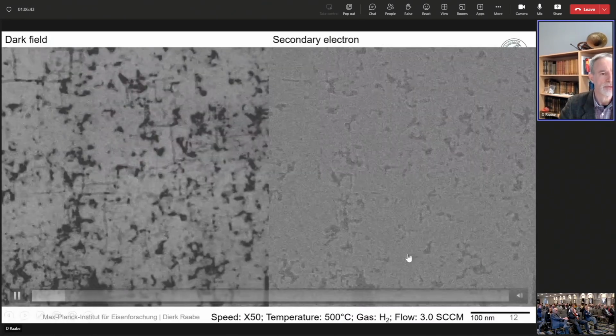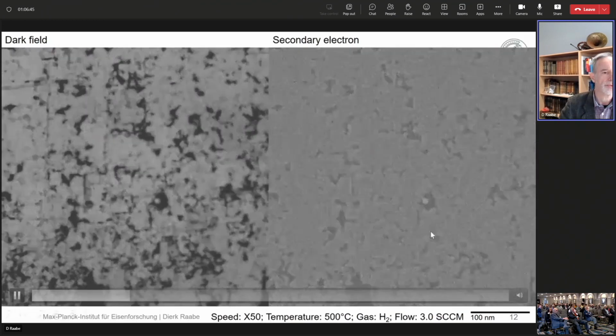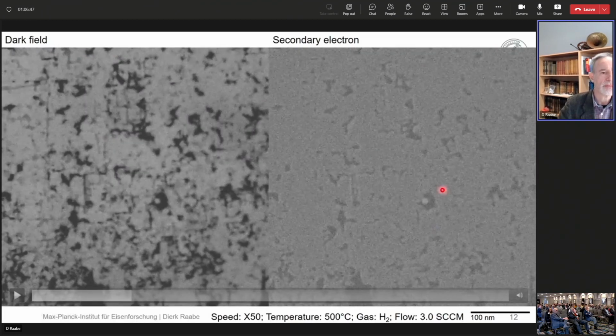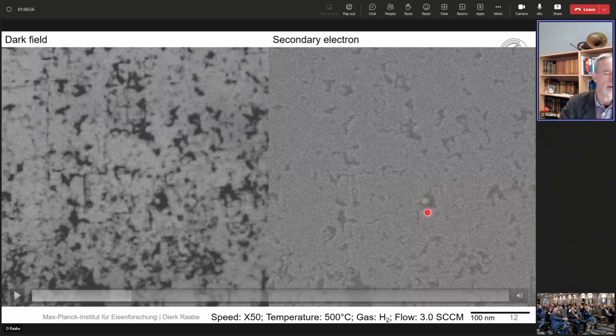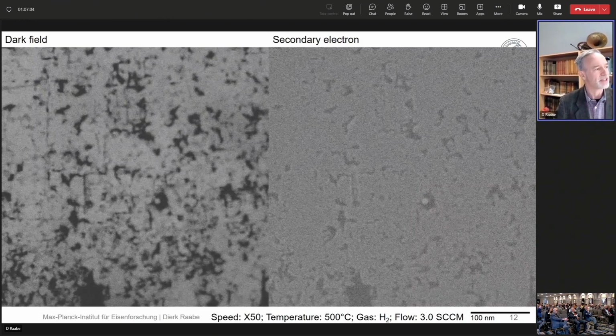And please be aware, note here where maybe you see the pointer. I stopped the movie here, and I hope you can see it. You see maybe this bright appearing little sphere, this little bullet type of feature here in this otherwise free volume area. And the free volume is a part of that transformation. It's thermodynamically very, very interesting because you cannot undergo these transformations without losing volume. That's the point of it. So we are here, so to say, in a grand canonical setting and not in a canonical setting.